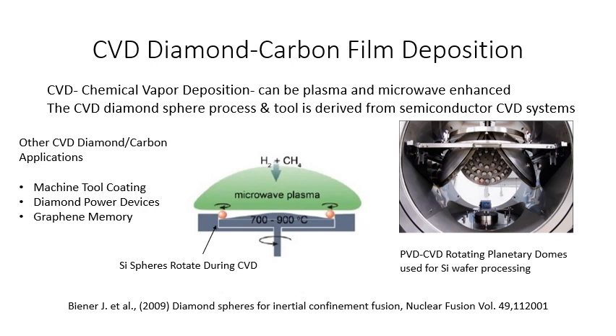And again, to make the spheres uniformly coated while you're depositing the diamond film, you've got to move and rotate these balls so the material is being sprayed or coated onto the exterior surface. Again, this leverages machine tool coating, diamond machine tool coating. It leverages diamond and graphene film deposition for semiconductor devices, because diamond and graphene or carbon are being used in advanced semiconductor devices as well. So this type of know-how in the semiconductor industry was leveraged to make the shell that coats the silicon sphere.